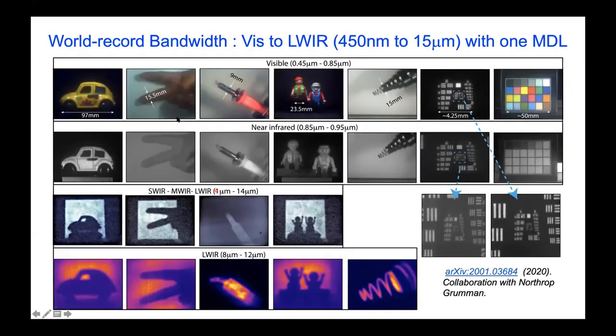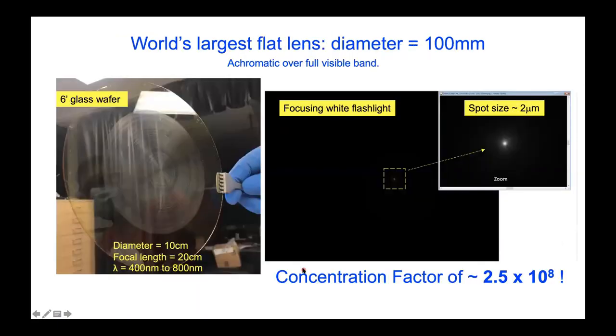Oh, I should also mention, in order to actually get this to work, we need to use substrates like diamond or something that is transparent. We also did another way to do the experiments where we actually make the lenses on two different substrates, the exact same lens on a silicon substrate and on a glass substrate. So use the glass to measure these and silicon to measure these as well. But essentially it's the same lens, just different support substrates.